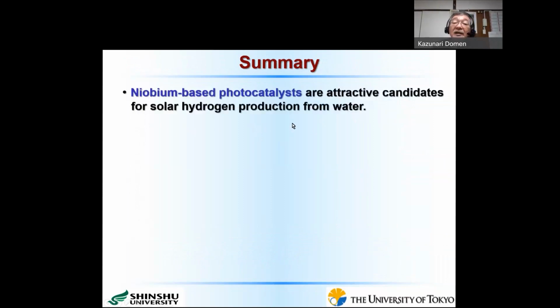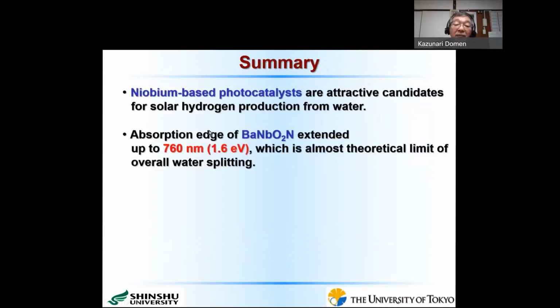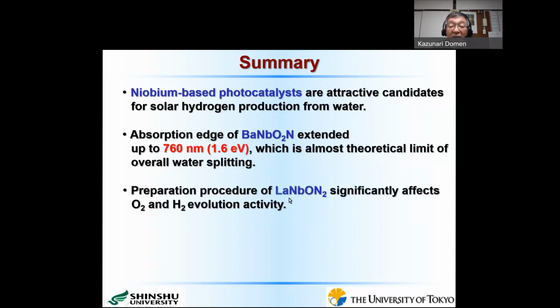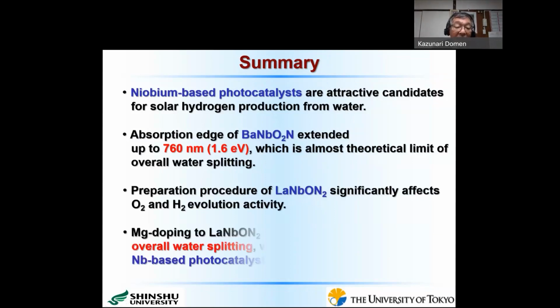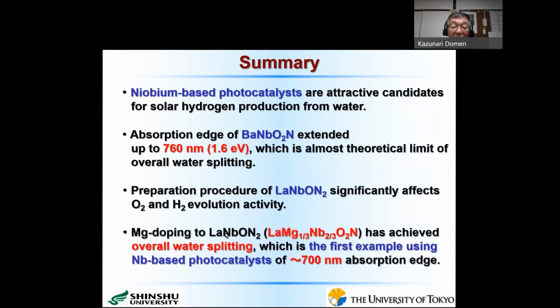Niobium-based photocatalysts are attractive candidates for solar hydrogen production from water, and the absorption edge of barium niobium oxynitride extends up to 760 nanometers, that is 1.6 eV, which is almost the theoretical limit that can split water into hydrogen and oxygen. And the preparation procedure of lanthanum niobium oxynitride significantly affects oxygen and hydrogen evolution activity. And as I showed in the last slide, magnesium doping into lanthanum niobium oxynitride, lanthanum magnesium niobium oxynitride, has achieved the overall water splitting reaction, which is the first example using a niobium-based photocatalyst, with an absorption edge close to 700 nanometers.